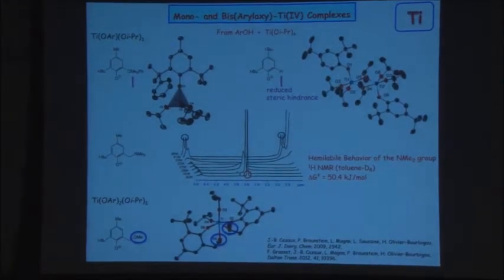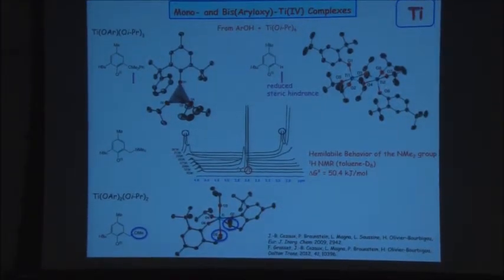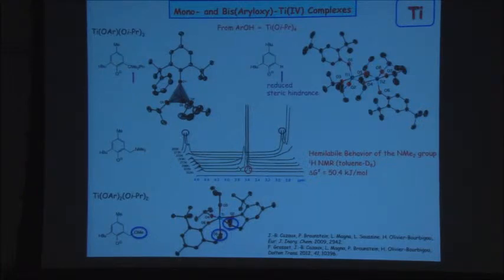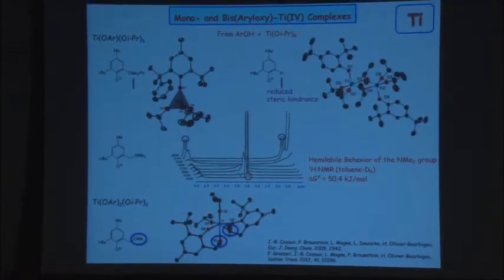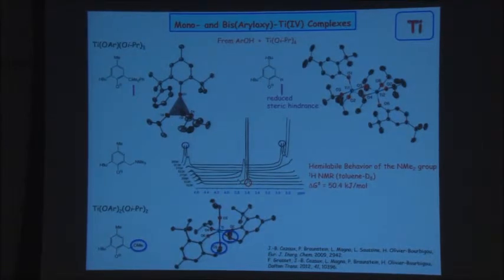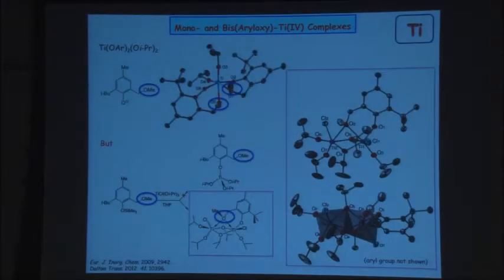It prefers oxygen donors. But still, I believe that in solution at low temperature, the preferred form is the one where chelation of the nitrogen to the titanium center occurs. So then we have this hemilabile behavior, this opening, closing of the gate, which, as I said, is key for catalysis. That may have some implications there. This is the compound I have just showed you before.